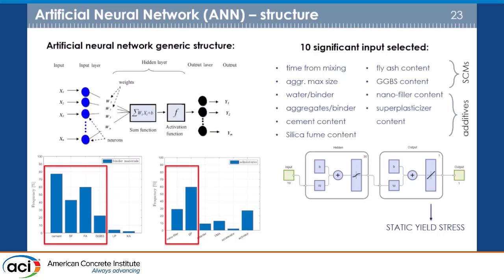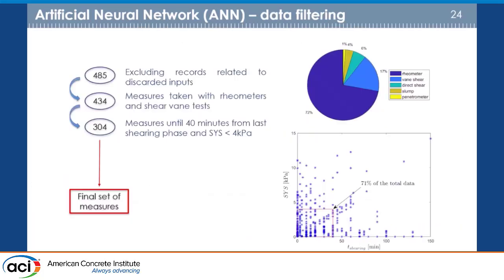Well, this is quite a hard task because in the majority of the papers on 3D printing, the information on the mix design is obscure, foggy, given in strange proportion ratios, because of industrial protection reasons and so on. As a matter of fact, this makes it difficult to have a consistent set of data that you need to feed a data analysis tool. We wanted in the beginning to end up with a double output network for both yield stress and viscosity, but viscosity is not as important for the 3D printing process. On the other hand, if the yield stress is not always present in all the papers, the viscosity is even less present, so in that case it was even more difficult.